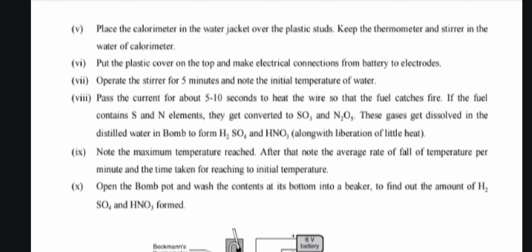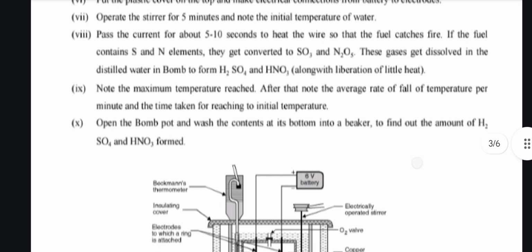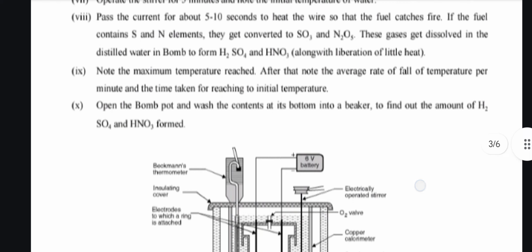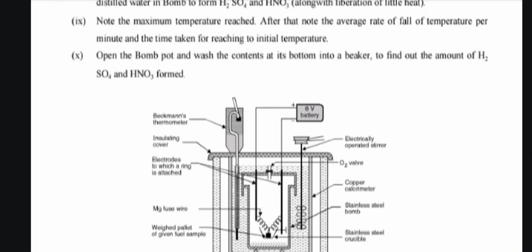Seventh is to operate the stirrer for 5 minutes and note the initial temperature of water. Eighth is to pass the current for about 5 to 10 seconds to heat the wire so that the fuel catches fire. If the fuel contains S and N elements, they get converted to SO3 and N2O5. These gases get dissolved in the distilled water in the bomb to form H2SO4 and HNO3. Next, note the maximum temperature reached. After that, note the average rate of fall of temperature per minute and the time taken for reaching the initial temperature. Last one is to open the bomb pot and wash the contents at its bottom into a beaker to find out the amount of H2SO4 and HNO3 formed.